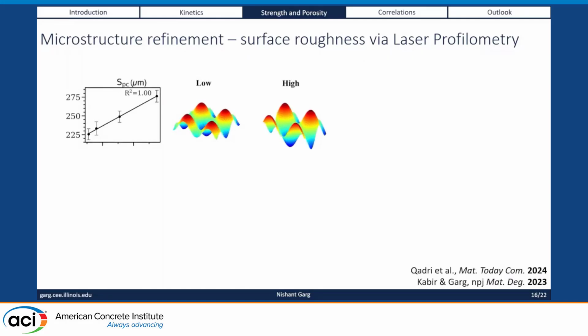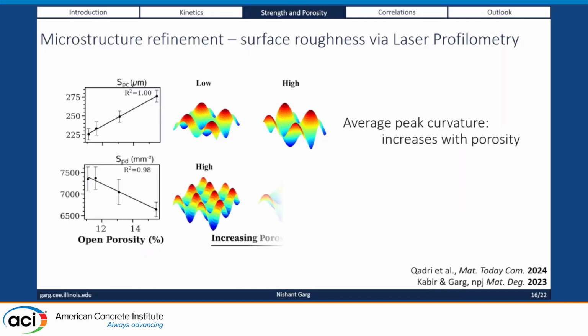And there is a paper I'm going to mention here at the bottom. We've spent a lot of time on this NPJ Materials Degradation paper last year, and we find some really interesting correlations between the profilometry data, the surface roughness and the porosity of a system. So I think this technique could have a lot of potential to explore. At this point, we just correlate two of the parameters. One is the peak curvature, and the other is the peak density. And we find that it actually correlates with the open porosity from the helium pycnometry.